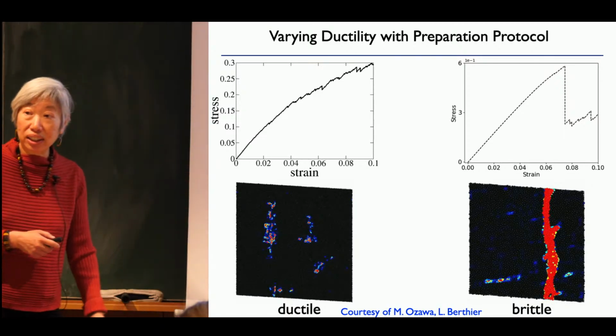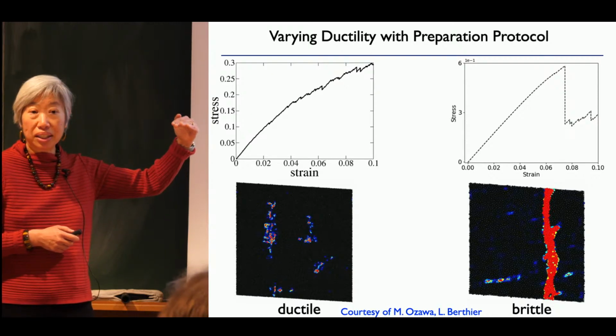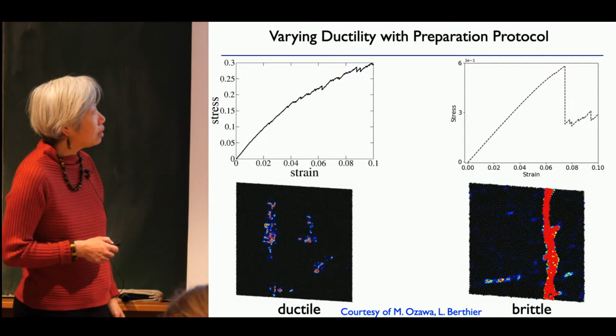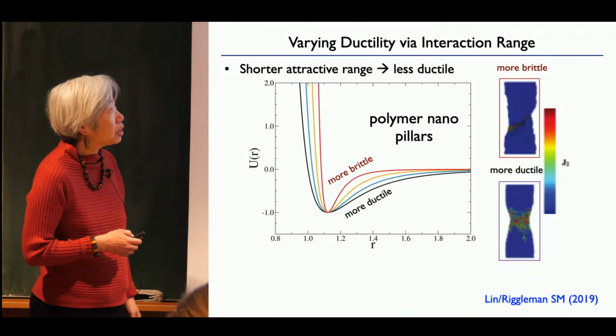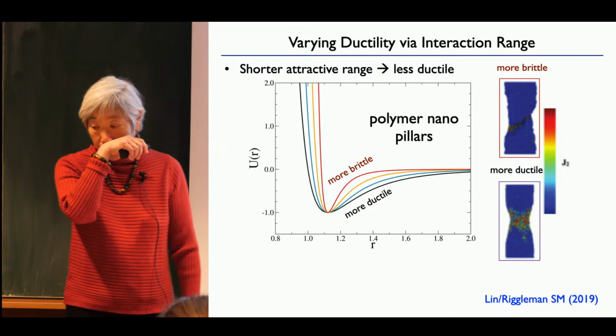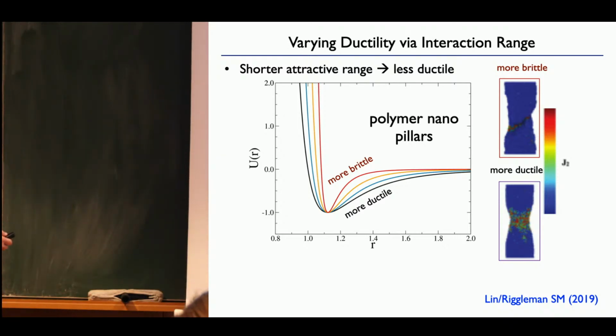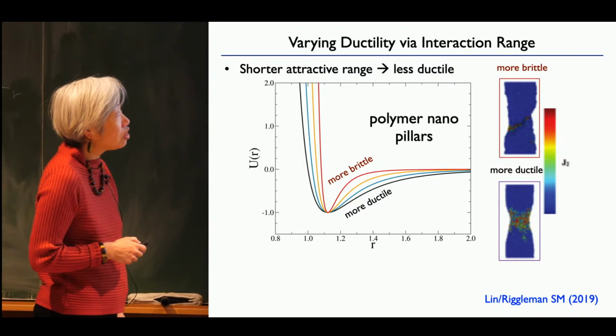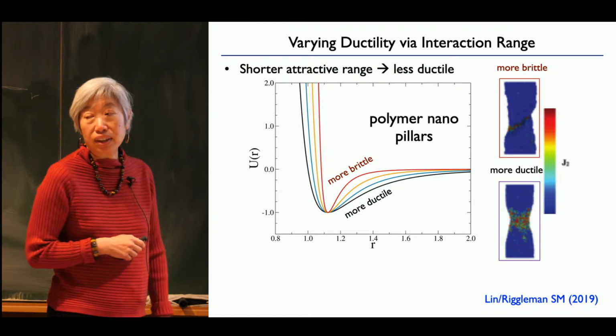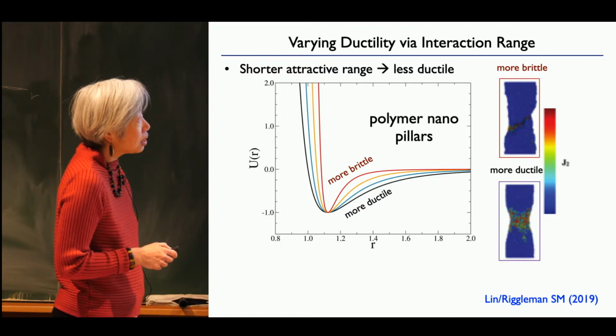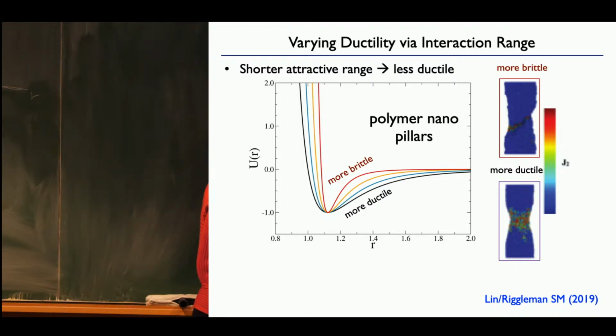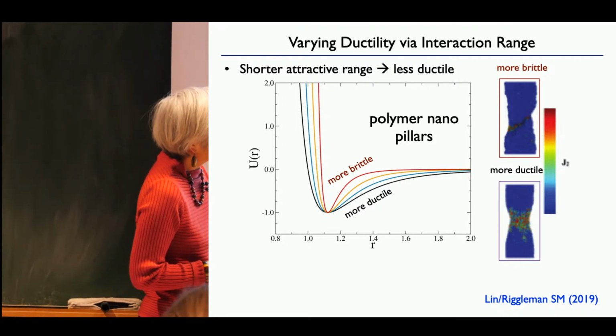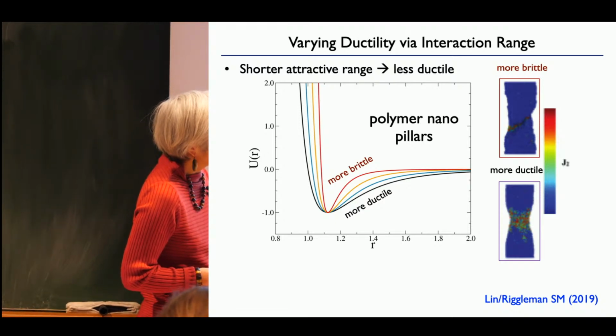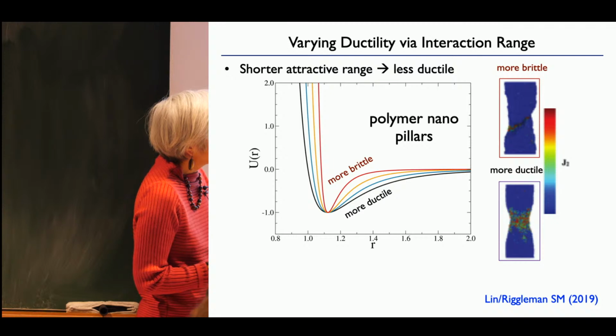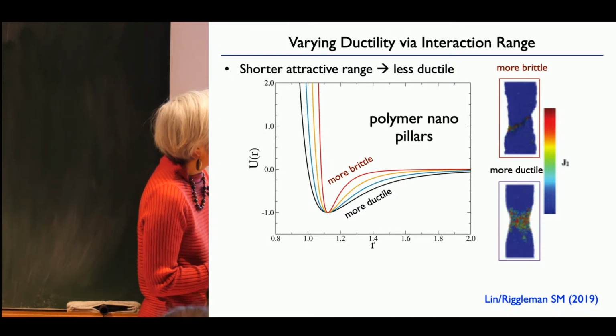So this is one way of controlling ductility, by how equilibrated the system is before you quench it. And the more equilibrated it is, the more brittle it is. Here's a different way of controlling the ductility, through the interaction potential. It turns out that systems with a shorter attractive range are less ductile. So here is the original Lennard-Jones, and as you shorten the interaction range, what you see is that the system becomes less ductile. So here's the original Lennard-Jones system, and here's the system with the shorter range.